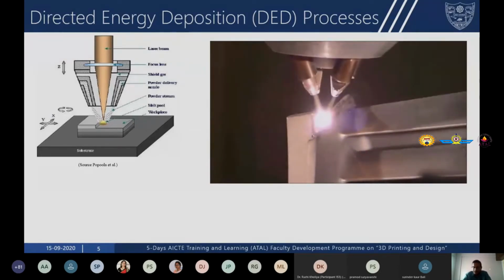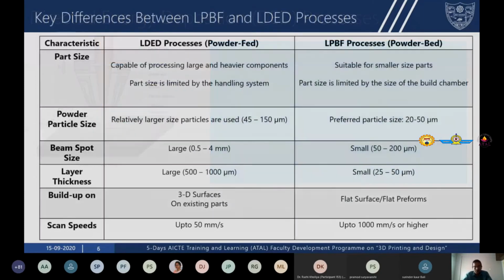So this is the second process, which is known as the directed energy deposition process. So some important differences between this process and the powder bed process that I showed earlier. Directed energy deposition is also known as the powder fed process, whereas the other is called the powder bed. In terms of part size, the directed energy deposition or the LDED process is capable of handling larger and heavier components when compared to the powder bed process. Here the part size is limited by the handling system, whereas in the case of the powder bed, the part size is limited by the build chamber. The build chamber volume is generally small.